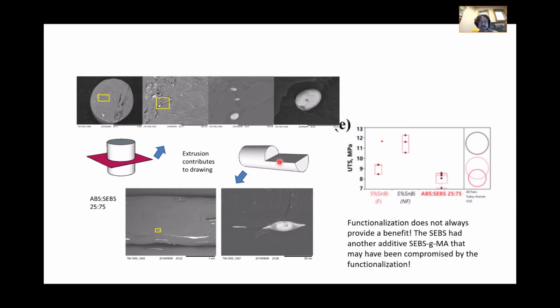And if we looked at the other section of this, just the filament, we see that we had wire drawing. Again we see that we drew, but when we compared the sample pools, we saw that the non-functionalized actually was the winner. So functionalization does not always provide a benefit. We showed a scenario where functionalization provided the benefit, and here another situation where functionalization does not provide a benefit.